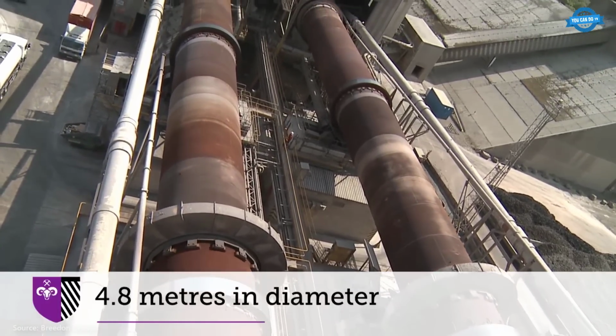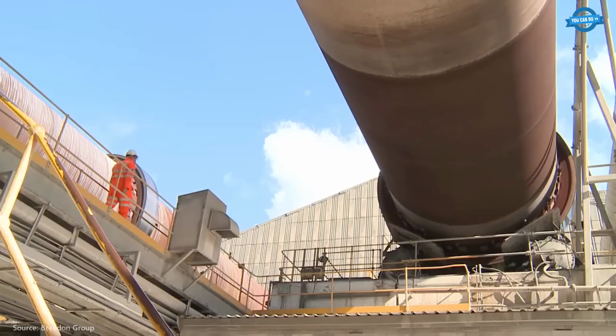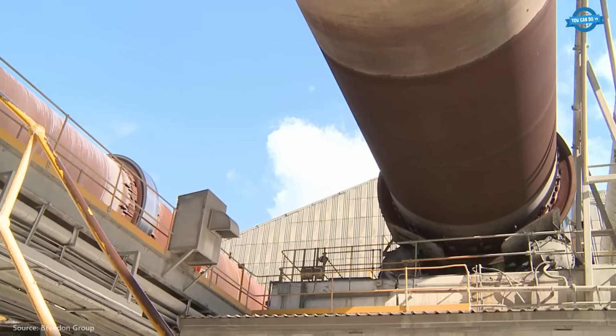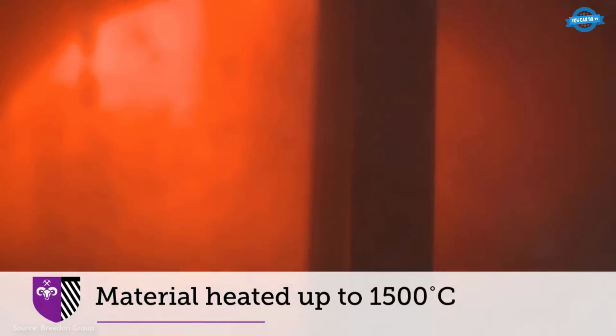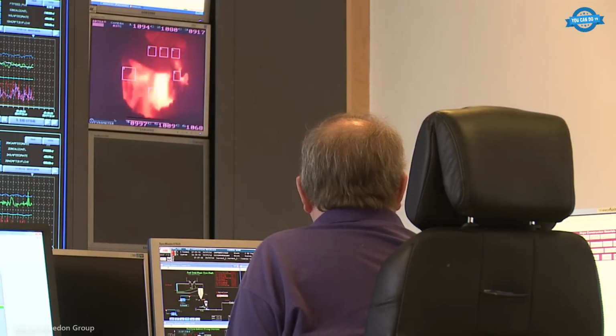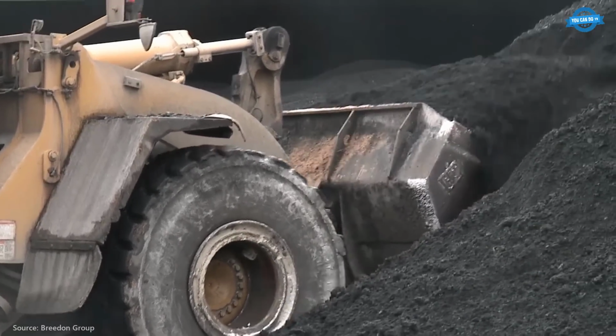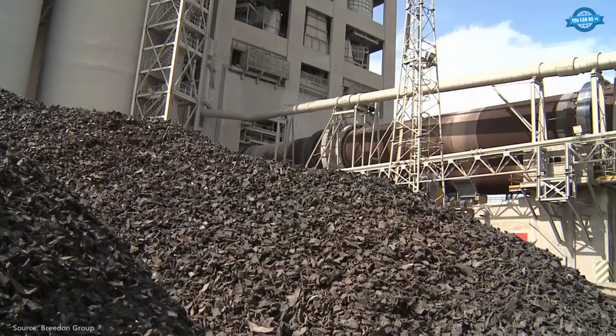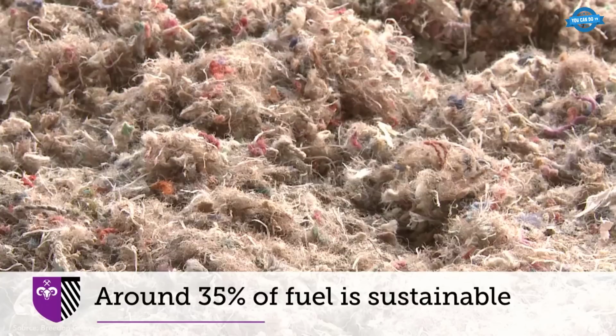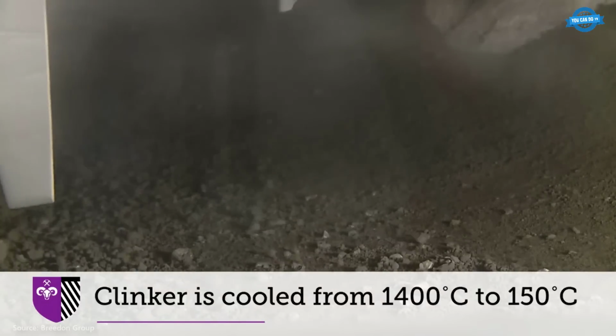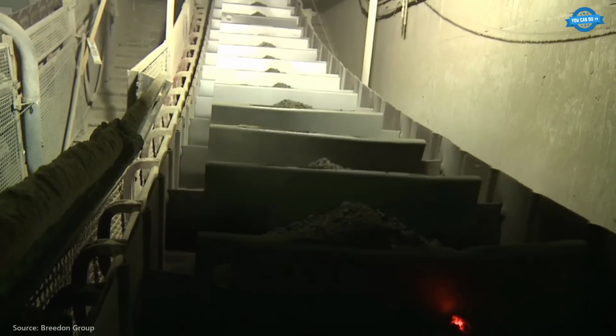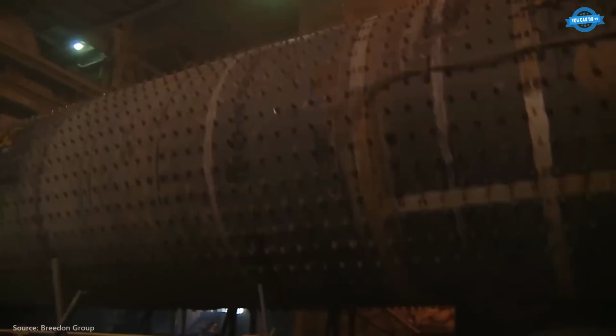Fuel for the kilns includes coal and sustainable alternatives like scrap tires and processed waste, with 35% of the fuel sourced from sustainable materials. Emissions are closely monitored and controlled to meet stringent environmental standards. Once formed, the clinker is rapidly cooled from 1,400 degrees Celsius to below 150 degrees Celsius and stored before being finely ground in cement mills. Additives like gypsum are introduced to control the setting time of the final product.